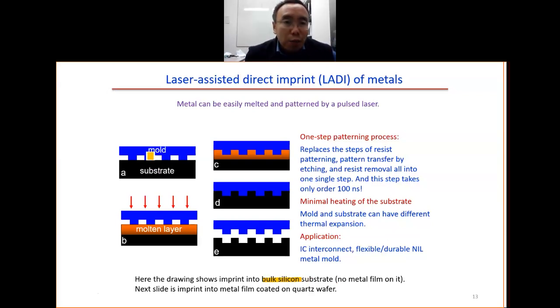Here you can see, first we press the mold onto the silicon substrate. Then we shine a laser pulse, so the top layer gets melted momentarily, for nanoseconds. Then the mold sinks into the substrate. Then you cool down and separate, and you get the pattern. This way, you can pattern the silicon in one shot. This happens within only 100 nanoseconds.